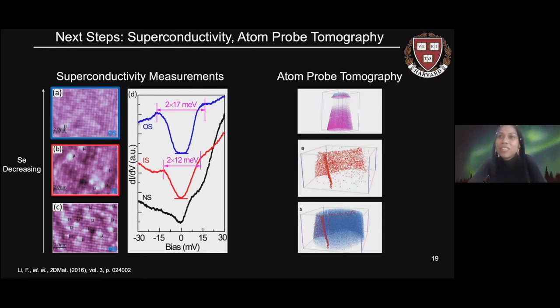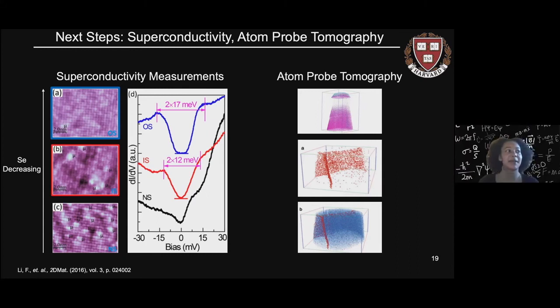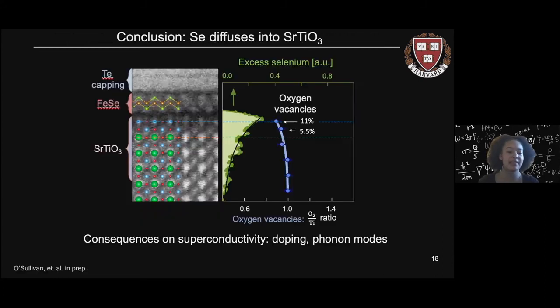Thank you. The next question is, how thick is your substrate? Would thickness affect your results? Great question. I don't know off the top of my head how many unit cells thick our substrate is. Here I present our STM image, which only shows 5 unit cells, but we had many more than 5. I unfortunately don't have a specific number for you, but the thickness should not impact the results of our measurement because we're focused on the interface, the region between the monolayer and the bulk. So after however many unit cells, we're not really interested in the behavior of the substrate itself, and the thickness wouldn't really change our results.